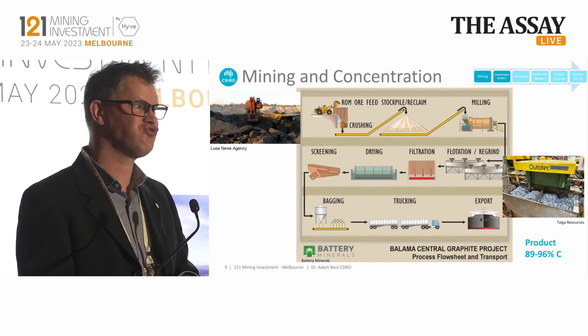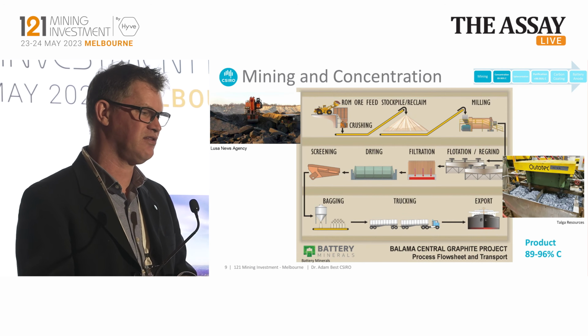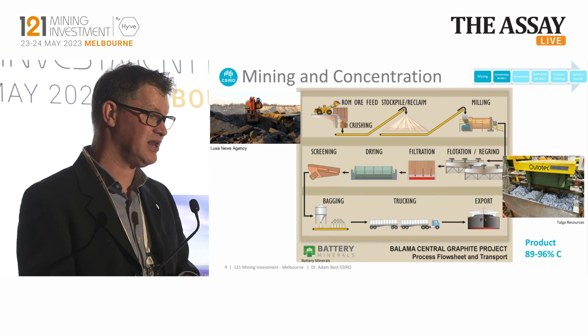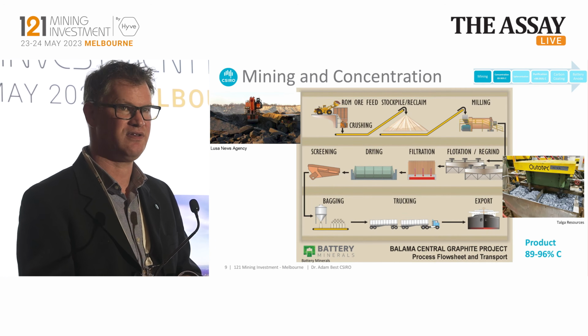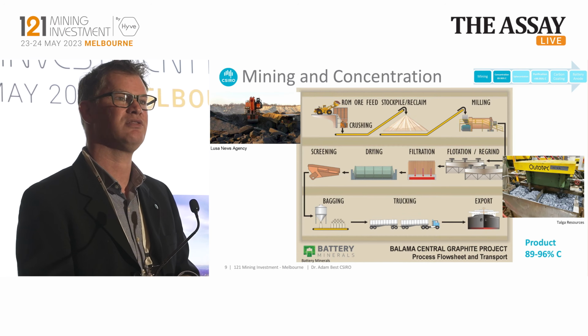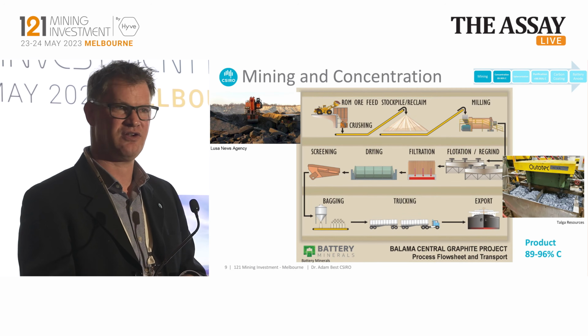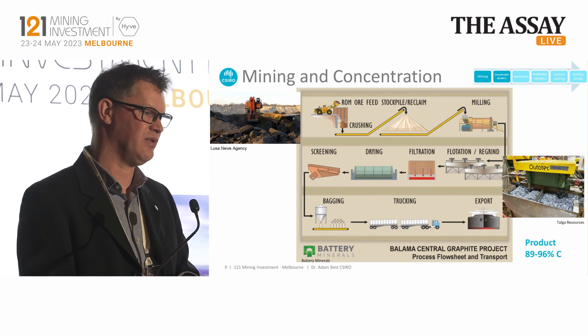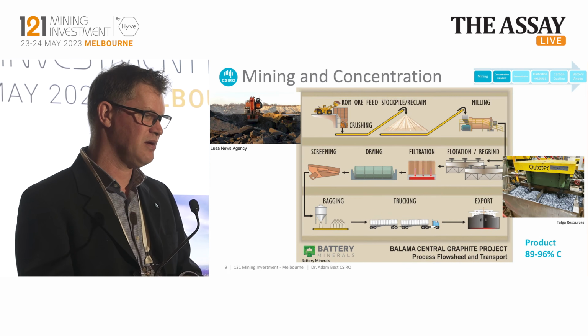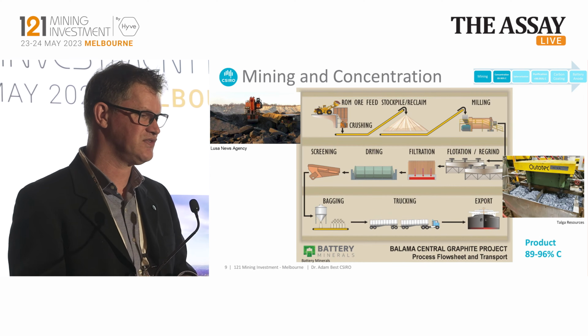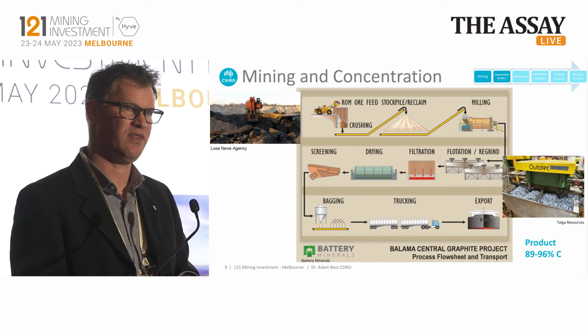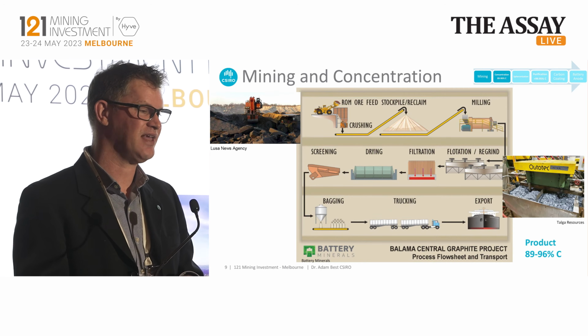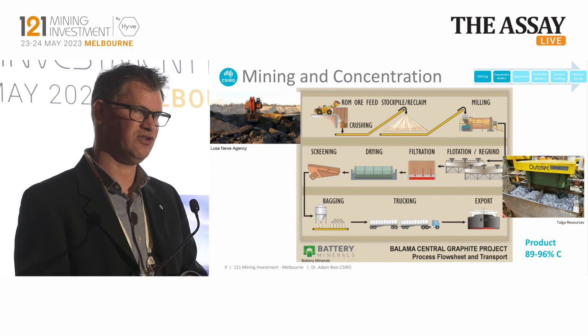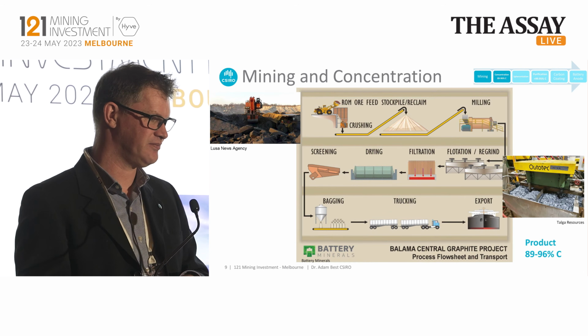So again, depending on the grade of material, you may need to have numbers of different milling and flotation and screening processes. The lower the grade, the more crushing, the more flotation, the more screening. The higher the grade, the less of it. So that has an energy penalty, so one needs to be mindful of that when going through those type of processes. But you can see here the screening into drying into filtration, followed by a further flotation and potentially more regrinding depending on how fine the flake is. The finer the flake, the harder it will be to recover. So you may need to do further regrinding and flotation as needed.